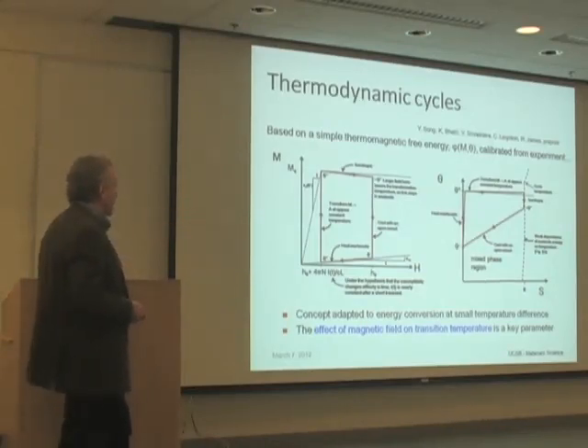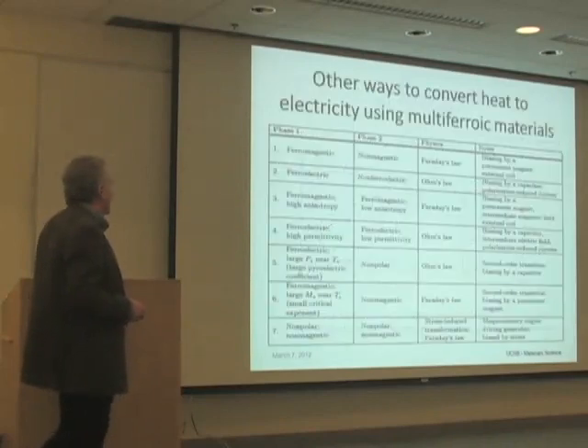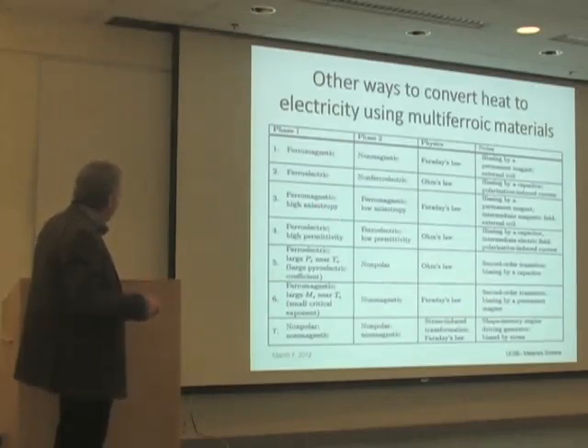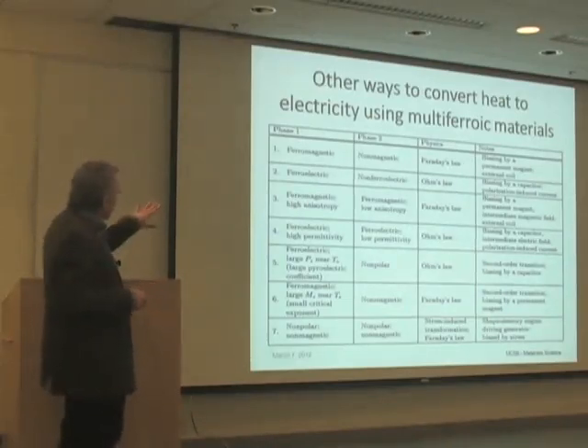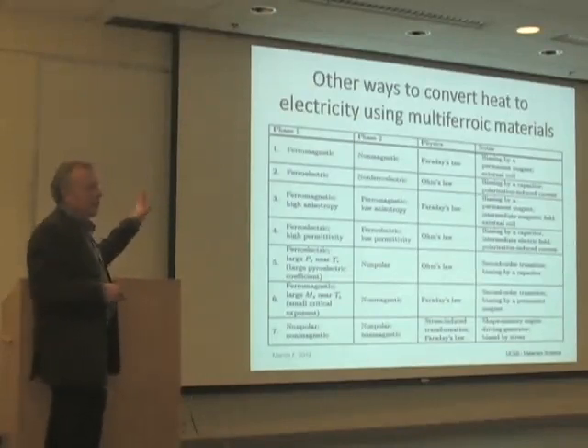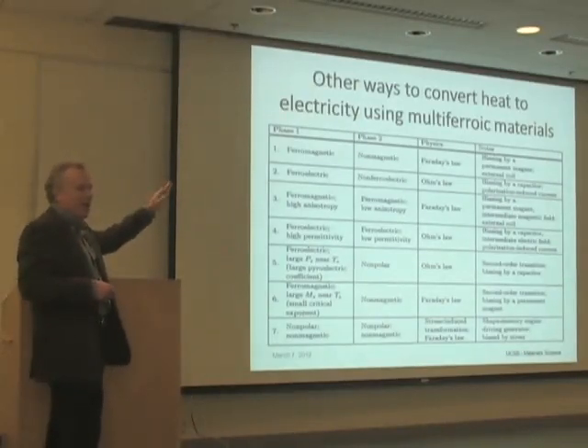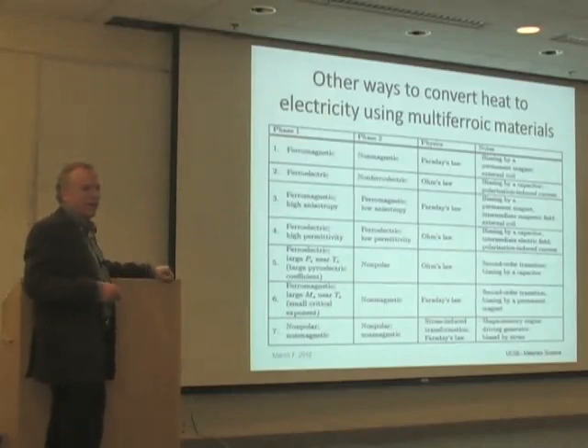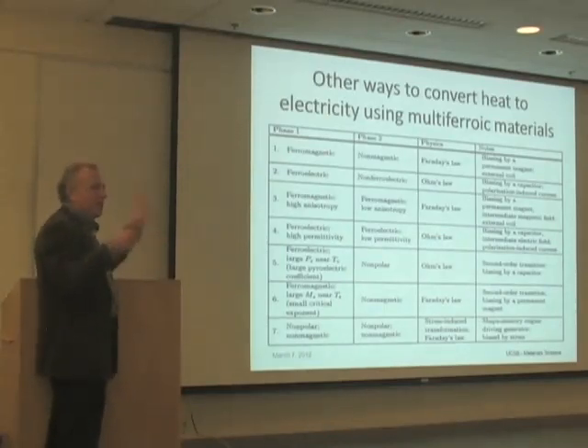We realized that using first-order phase transformations and many different electromagnetic properties, you can even use anisotropy. You could work at a kind of intermediate field, and by having high anisotropy and low anisotropy phases, but more or less the same magnetization, you could build an energy conversion device. Or instead of magnetization, you could use polarization. There are a huge number of ways to use this idea with first-order phase transformations.